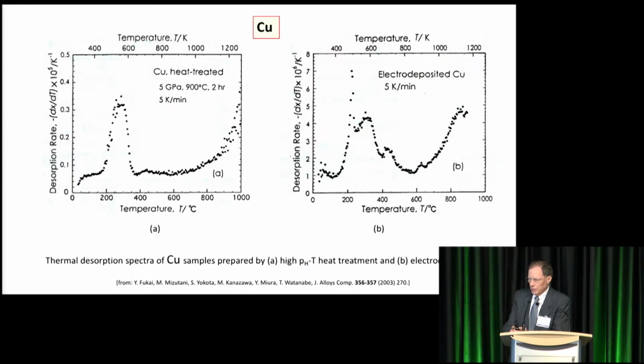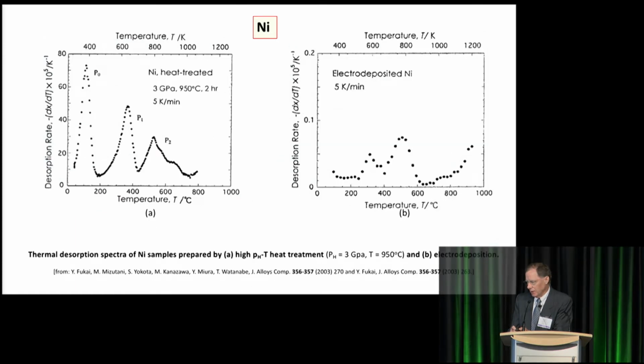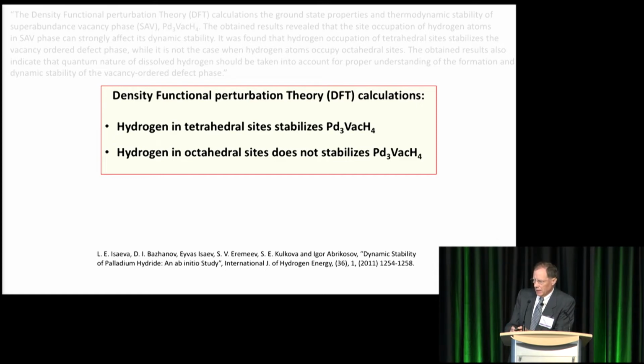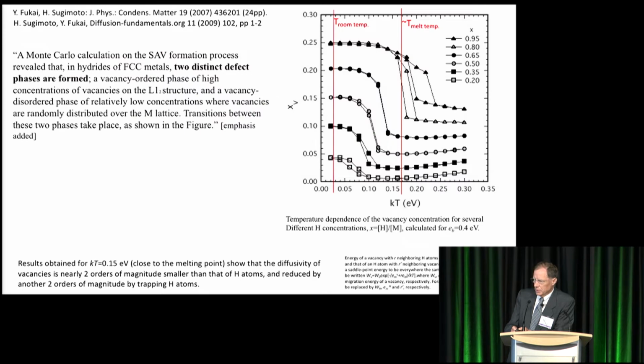I'm going to quickly go through this. This is part of the evidence for the presence of these superabundant vacancies, but the main point is that regardless of how you prepare them and how you create them, whether by high pressure, high temperature, or a co-deposit, you have the same thermal desorption. This is for copper, this is for nickel, and again, I'm going to have to skip the density functional perturbation theory calculations and some of the other supporting papers which report their findings in terms of calculations that these superabundant vacancies are in fact the most stable, the true equilibrium form of the alloy.